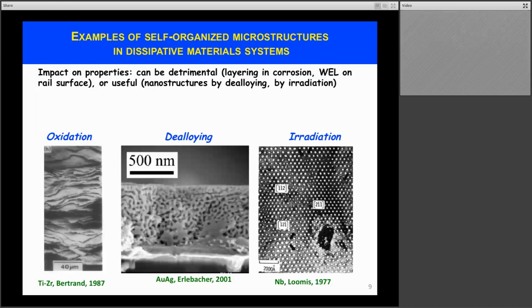But in some cases, self-organization could be useful. For instance, in de-alloying, as I indicated, you can control the size of the pores, and so that can be useful for filtering applications, and also it may provide materials with very high specific surface area, which can be good for catalytic applications.